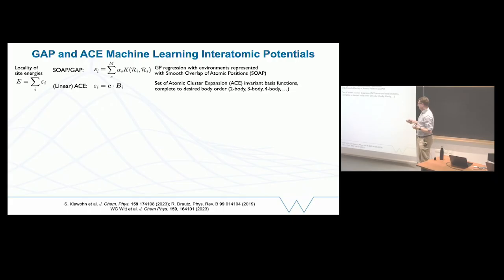In practice, you don't do that because you truncate at some body order: 2-body, 3-body, 4-body. So it's not a bijection, but you need that if you're going to actually reduce the number of descriptors that you have in comparison to your original dimensionality. Okay, so it's a recipe that gives you invariant basis functions. That's the sort of level of detail that I want to go into. I think we might hear more about some of these concepts later on. And that gives you a way to predict local energies. These coefficients, again, you obtain from a linear fit, so from least squares. Really, really easy. You evaluate these basis functions on all of your data points, and then you do a least squares fit, and you have a model which can give you local energies. You add them up, and you get total energies.